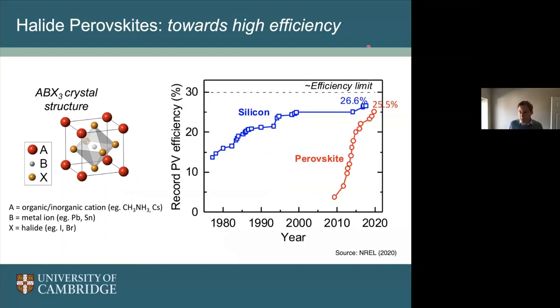And the reason they're creating a lot of excitement is because they're making very efficient solar cells. This is showing the efficiency of the solar cells over the last 30 or 40 years. You can see silicon here, which is essentially the workhorse system, is at about 26.6%. The perovskite is already approaching that, and probably will overtake it very soon. This is extremely exciting because it is a new material that has done this in just over a decade of development.